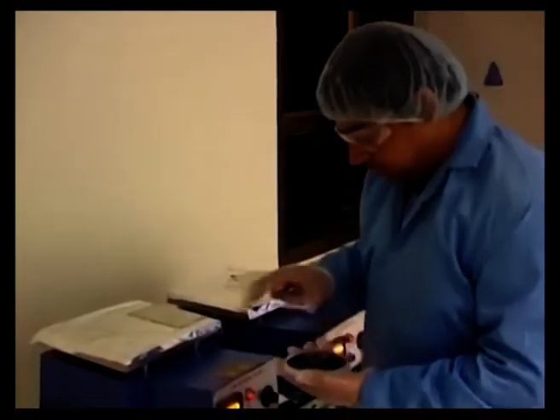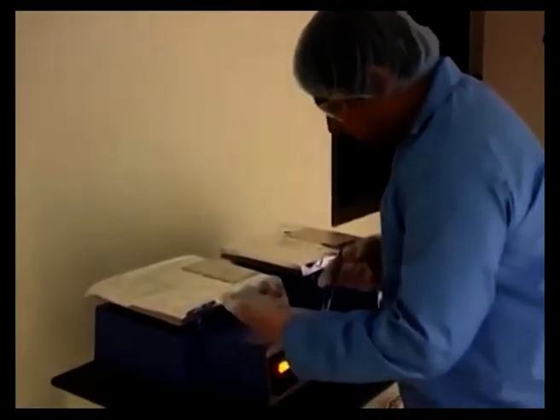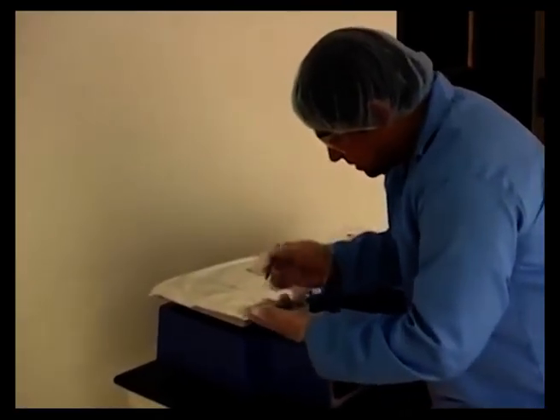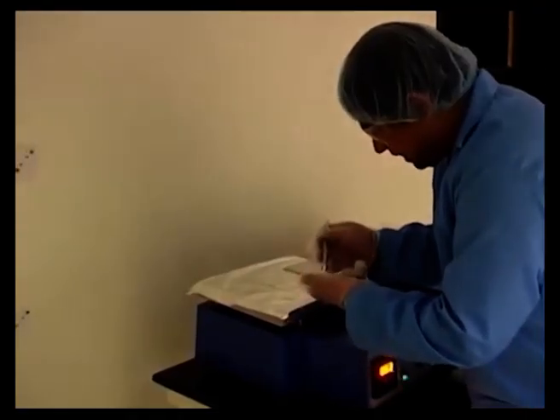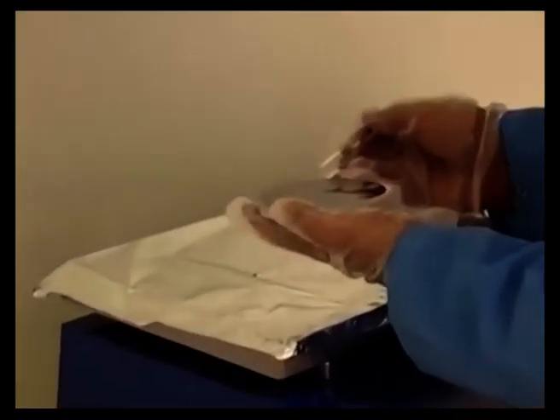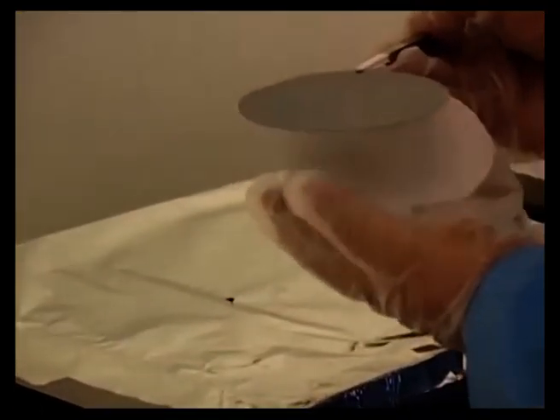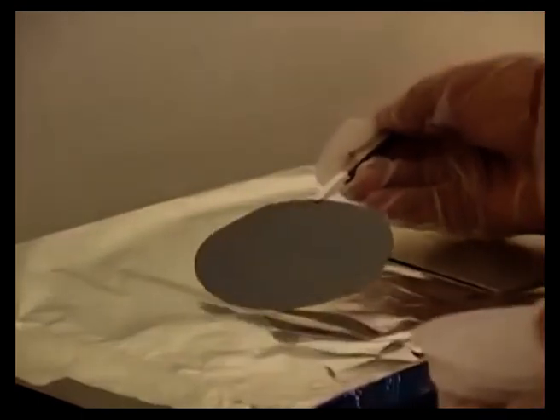So I'm going to put this wafer now on the top of this particular hot plate, which has been set at 65 degrees. So for doing that, we have to be again very careful about pulling this resist coated wafer out. We use the exact same area as we had used before for holding, just a small edge or a small corner, and then keep it on the hot plate. We have a stopwatch with us here.